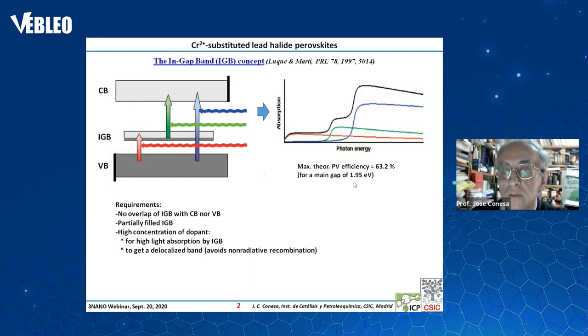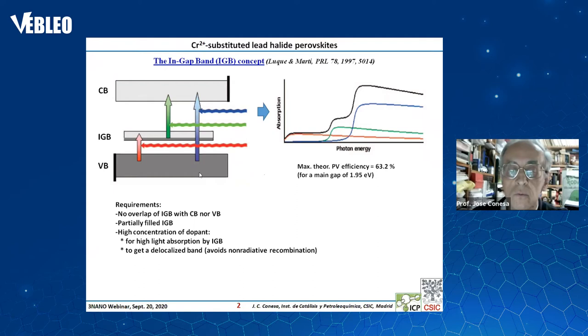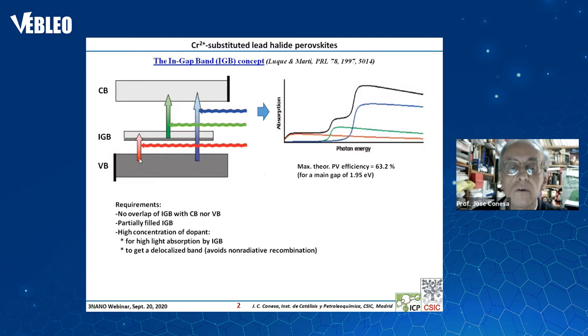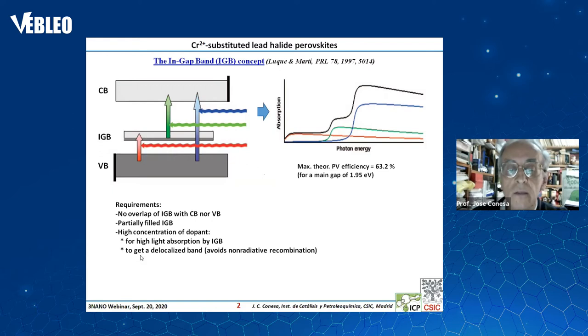In order to achieve this, several requirements are necessary. First, no overlap of the ingap band with the conduction band nor valence band, because in that case you would have just thermalization and no particular advantage. It is also very important that this ingap band is partially filled, which would allow electron transitions both from the valence band to the empty part of the ingap band, and from the filled part of the ingap band to the conduction band. Also, a high concentration of dopant is very convenient so that you can have high light absorption through the ingap band, and a delocalized band avoids non-radiative recombination.